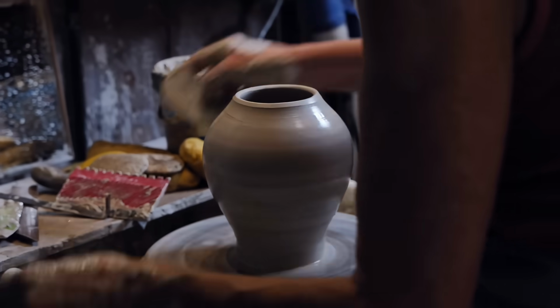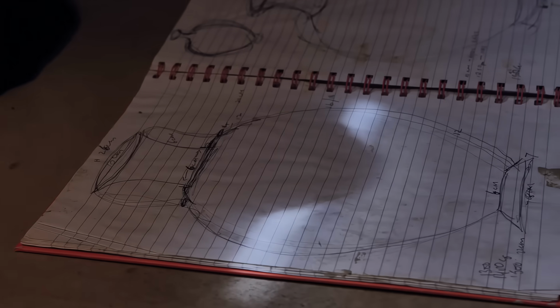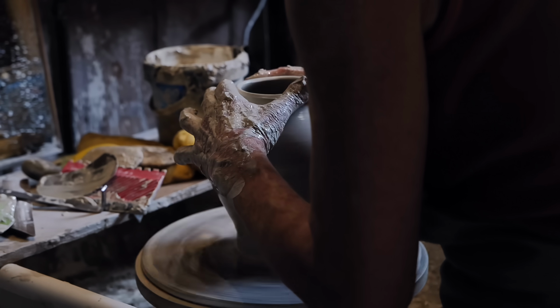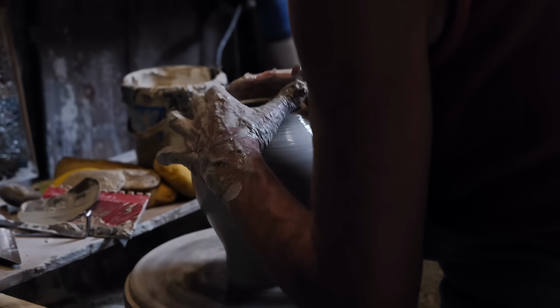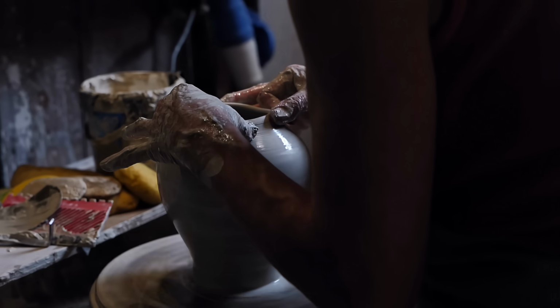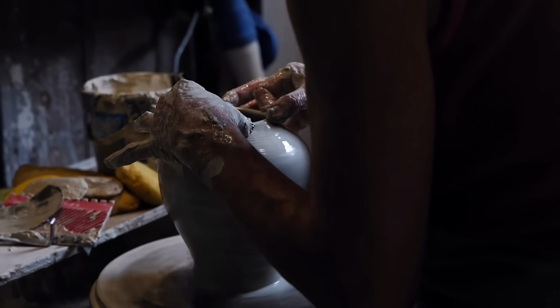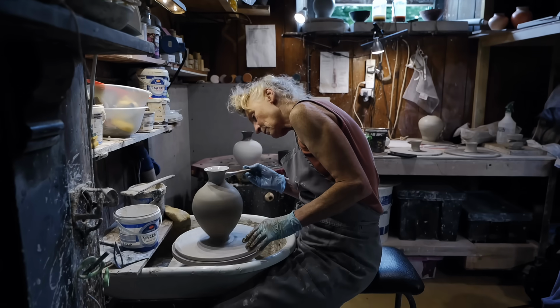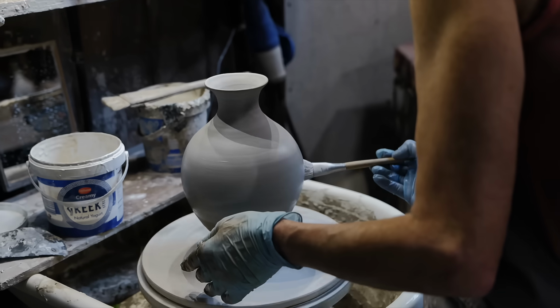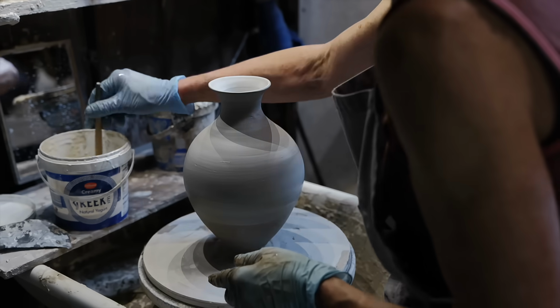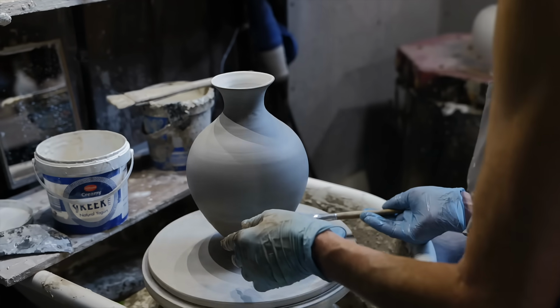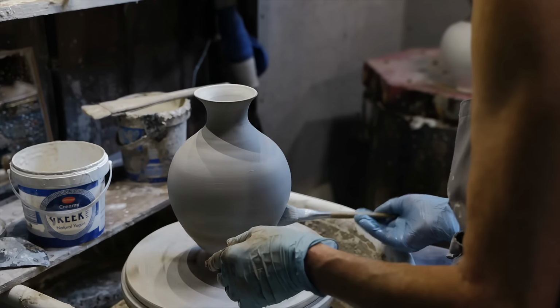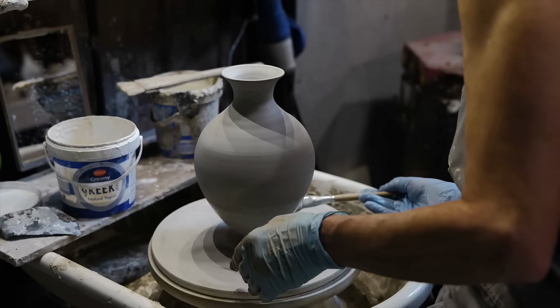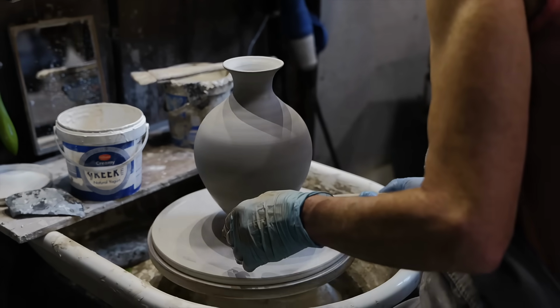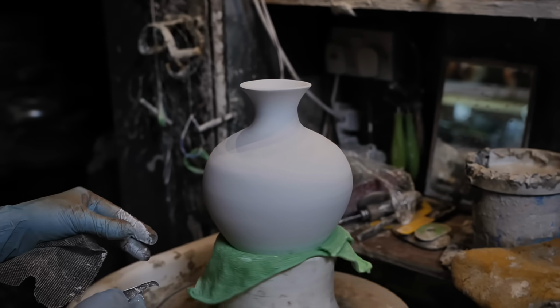All my pieces are thrown on the wheel. I like Greek and Roman traditional form and creating a very smooth surface on which to get patterns that come from saggar firing. I use a metal rib to smooth the surface, slightly burnish, especially if the clay is a little bit rough. I then brush on porcelain slip that's been sieved. I do about 3 layers until it gets very smooth, and then I'll wait for that to dry and sand it, and that's prepared the surface for applying terra sigillata.